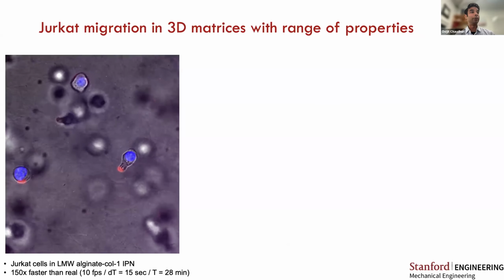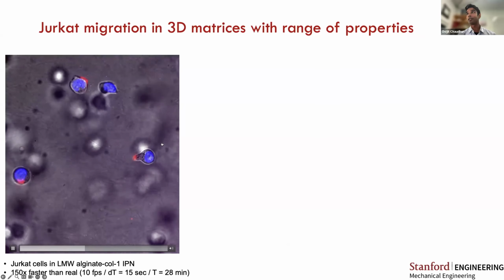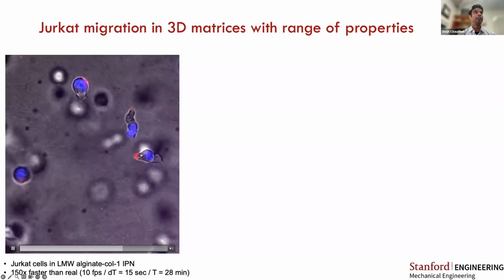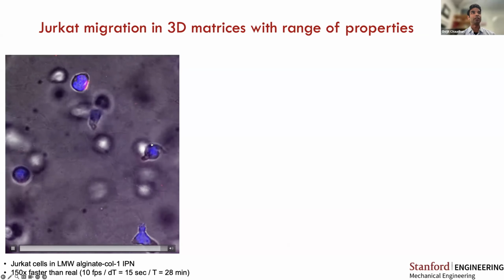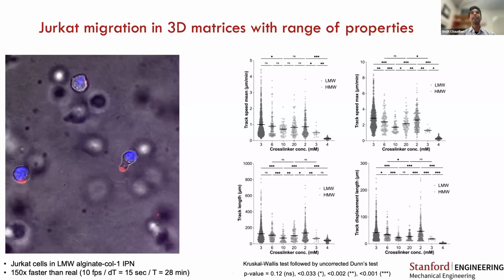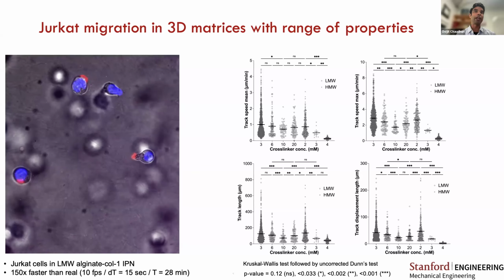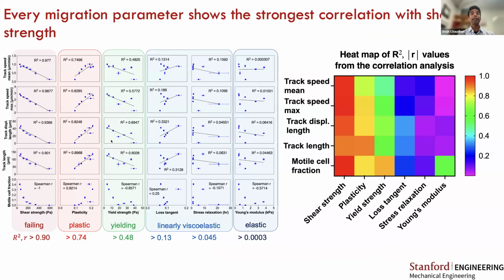Okay, so Byung-Hung first started by culturing Jurkat cells in these hydrogels. In red, we're looking at the actin cytoskeleton. In blue, we're looking at the nucleus. So we get migration, and we can track the migration speed, the percentage of cells that migrate, and the distance they migrate. And he did a number of correlation studies between these various migration characteristics and these various matrix properties. And strikingly, for each of these migration characteristics, the strongest correlation is with shear strength. And there's actually very little correlation with stiffness, stress relaxation, or the loss tangent.